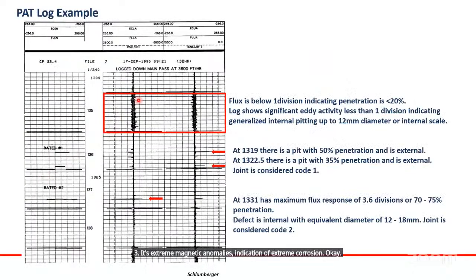This is the presentation of the PAT log. As you see here, we have the eddy current upper array, the flux leakage upper array, the eddy current lower array, and the flux leakage lower array. Flux is below one division. As you see here, there are 1, 2, 3, 4, 5 divisions. Below one division indicates penetration of less than 20%. The log shows significant eddy activity of less than one division, indicating generalized internal pitting up to 12 millimeter diameter, or internal scale. So from this division, and according to the code, we will know the severity of the corrosion itself.